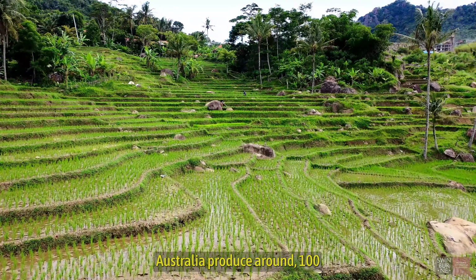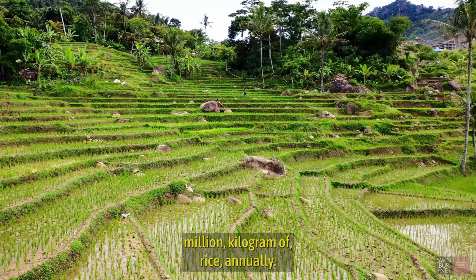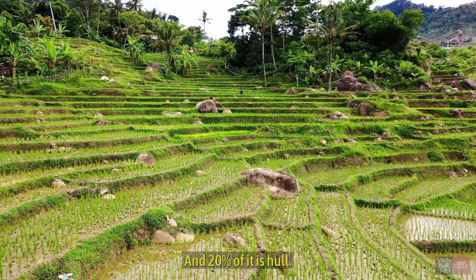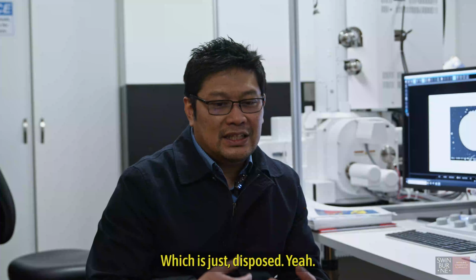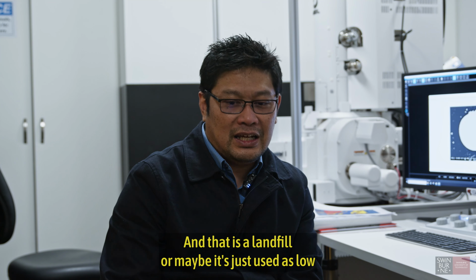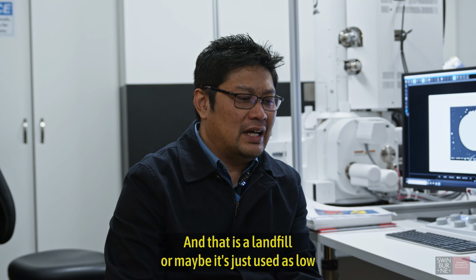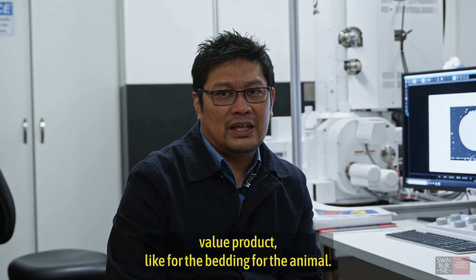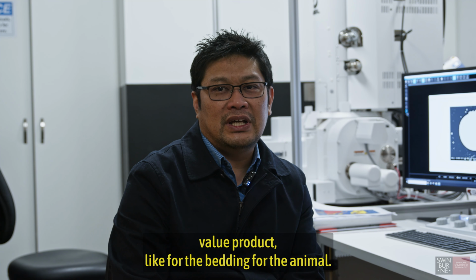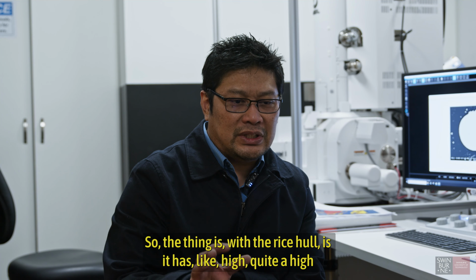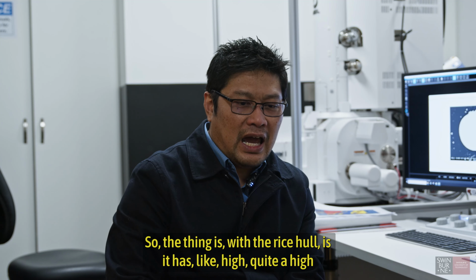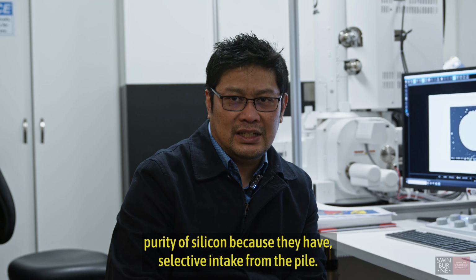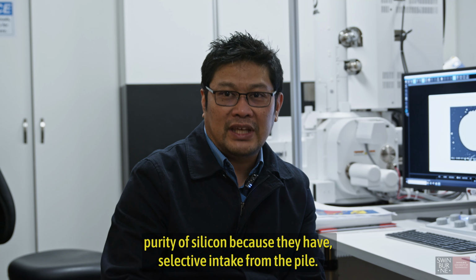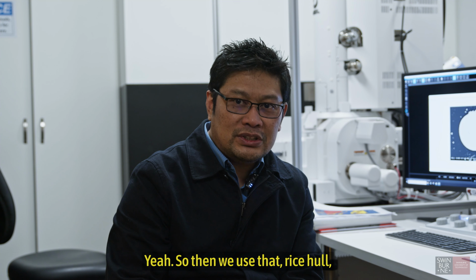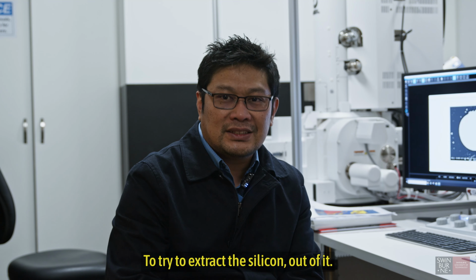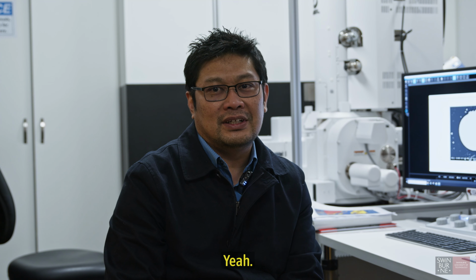Australia produces around 100 million kilograms of rice annually, and 20% of it is hull, which is just disposed of, either as landfill, or maybe as a low value product, like bedding for animals. The thing is, rice hull has quite a high purity of silicon, because the plant has a selective intake. So we use that rice hull to try to extract the silicon out of it.